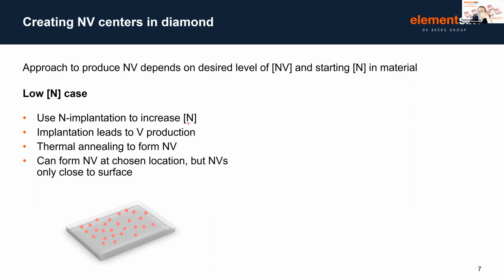So essentially we can implant single, if we want to, nitrogen atoms into that substrate. Now the process of implantation also leads to vacancy production, essentially a little bit of damage around that nitrogen atom that we've implanted. We can then thermally anneal the diamond at temperatures above which vacancies are mobile, which is typically above around 800 degrees C, and the vacancies will find a nearby nitrogen atom and form the NV that we're after. So with this technology, we can form NVs at chosen locations, but the NVs are only found close to the surface. Ultimately, an implanted nitrogen atom can only penetrate so deeply into a diamond substrate. So that's the low nitrogen case.